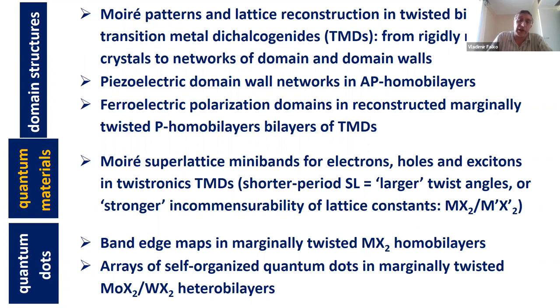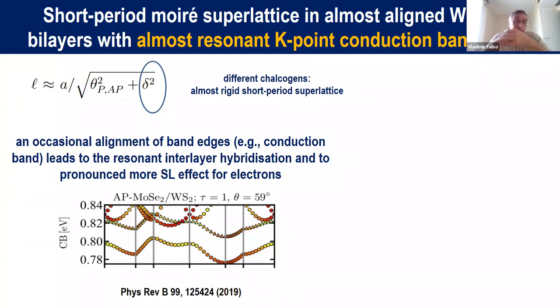And the physics in this case is more or less the physics of moiré minibands, where you can take into account the interlayer hopping between the layers, which is also periodically modulated, taking into account this change of the interlayer distance and the influence of the local stacking on the interlayer hopping matrix elements. Obviously, the interlayer hopping is the strongest when you have band edges as close as possible to each other in the two layers. Such a situation is realized in molybdenum diselenide and tungsten disulfide heterostructures for the conduction band edge. And then there is a bit of resonant interlayer hybridization for electrons at the K points of the hexagonal Brillouin zone of the crystal, which represent in monolayers the band edges, both in the conduction band and also in the valence band.